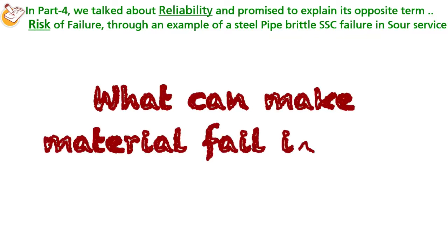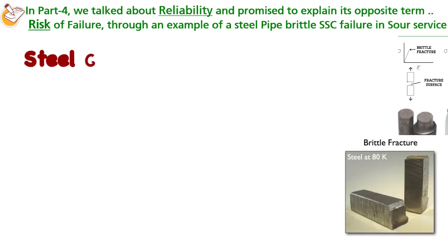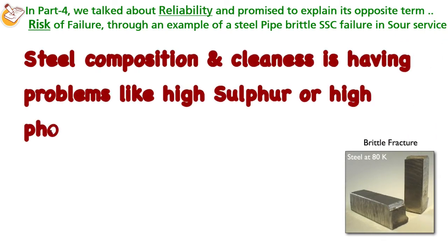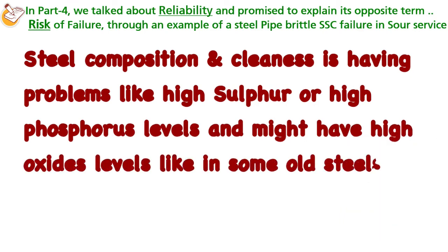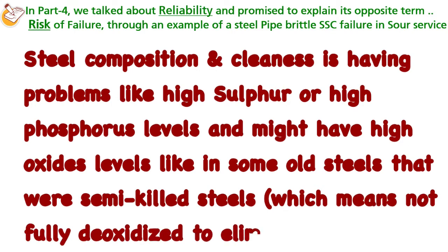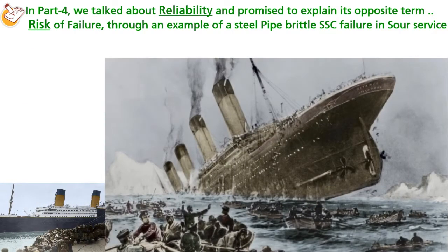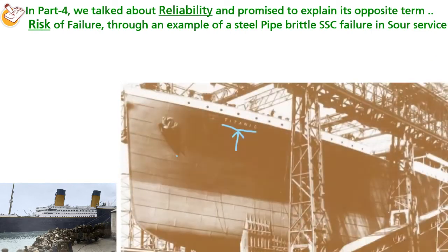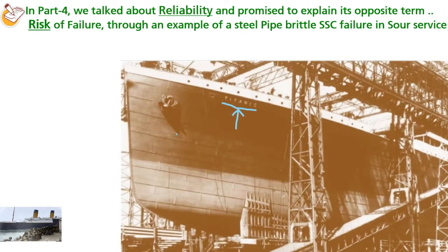But what can make material fail in such a brittle mode? Some causes can be that the material itself has problems, like high sulfur, high phosphorus levels, and high oxide levels, as in some old semi-killed steels, which means not fully deoxidized to remove such oxides. The most famous disaster with a brittle fracture due to this type of steel, in combination with low temperature and impact load, is the famous 46,000-ton Titanic steamship disaster in 1912, with 2,227 passengers and crew aboard, where complete brittle fracture took place in the hull after striking the iceberg at high speed with its side. It was after this collision that the disaster started, and the very low water temperature increased the steel brittleness.